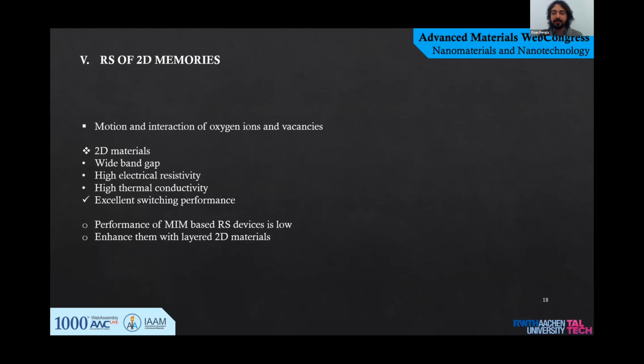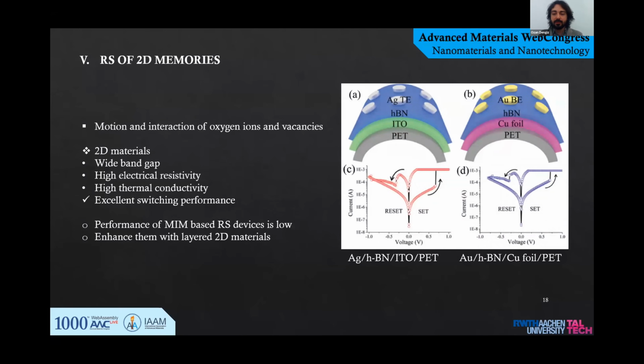Physically, RS is related to the motion and interaction of oxygen ions and vacancies. Therefore, especially materials with wide band gap, high electrical resistivity, and high thermal conductivity can offer excellent switching performance for the RS memory. This figure shows the schematic of devices made from these materials with their switching characteristics. As mentioned before, the performance of MIM-based RS devices may be enhanced with layered 2D materials.